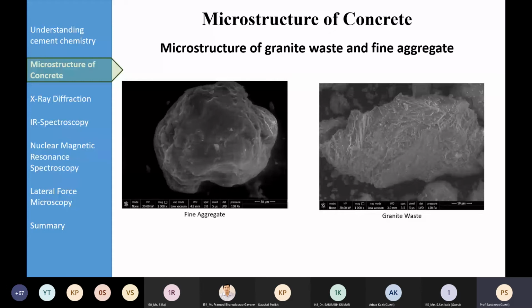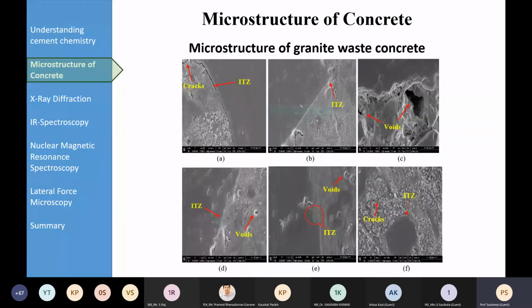Like here you can see the microstructure of granite waste concrete. When it was put in the concrete, this ITZ is clearly visible here. These voids here are clearly visible. This very clearly visible ITZ here. And then these are cracks. And you can see these voids are visible here. ITZ, again these voids and this ITZ. So these features can be easily identified by going through scanning electron microscopy.